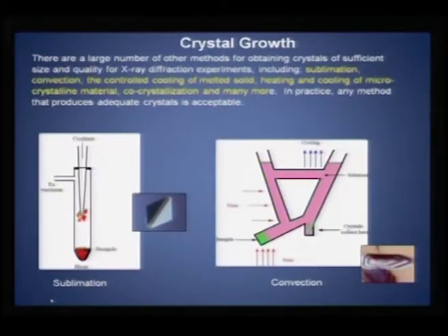And another one, which is almost a common protocol in any chemistry lab practice, is sublimation, where you take the sample and heat it in vacuum, and in the cooler part you have a cold finger which is chilled. So in the cooler part of the setup you see the crystals crystallizing or depositing. This can be a very good and the most inexpensive way of isolating crystals.